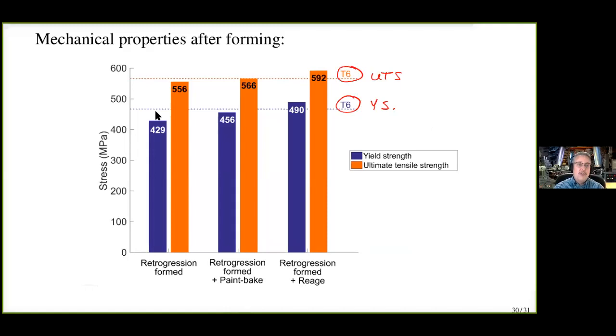Retrogression formed, you see we have a drop in the strength here. The paint bake actually got us pretty close in yield strength and back to almost tensile strength, which tells us that the strain we're inputting to the part during forming may affect the reaging process. The full reaging process, you can see we actually ended up with a stronger part than we started with.